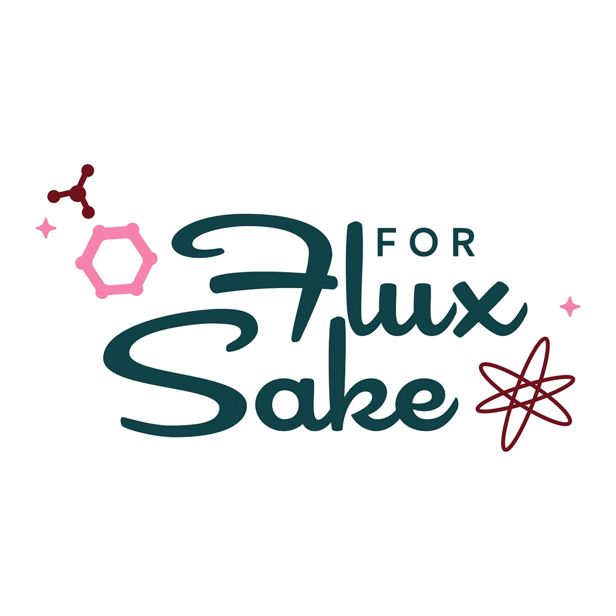It's not wrong. The problem that happened with Gerstley borate in the 20th century is that people found they could take a glaze at cone 10 and just throw 10% Gerstley borate into it, and it would probably work at a mid-temperature range. The problem is that's really bad chemistry. Because no matter what people say, even when we say something's cone 6, it's not cone 6. It's what temperature that specific chemical reaction is done. And that may be cone 6.5.